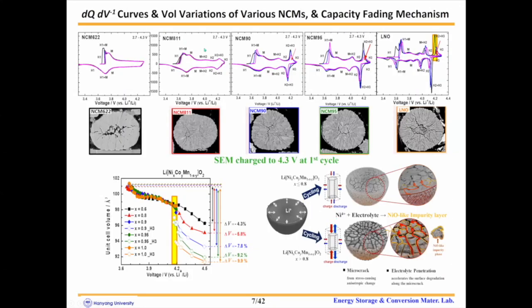This is the dQ/dV curves and the volume variation of various NCM cathode materials. As you can see, NCM 90 and 95 and the pure LNO exhibit four distinct redox peaks due to multi-phase reactions from the H1, the monoclinic, and the H2 and H3 phases. And the redox peaks became polarized and reduced in height with cycling, especially in the H2, H3 phase transitions. On the contrary, these redox peaks of the 622 and 811 hardly change during cycling.